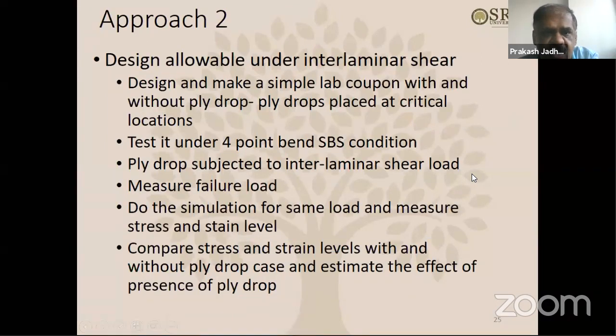What about shear? So for shear, we design another coupon. Here again, we thought let's design another coupon, okay, where we'll put the ply drop exactly at the location where interlaminar shear is more, like interlaminar shear level is very high. So we decided to use the short beam shear kind of specimen and use the four-point bend for short beam shear. Okay, so here ply drops will be subjected to the highest level of interlaminar shear load, then measure the failure load, do the simulations. Again, the same procedure basically, and also measure the initiation failure load using the acoustic emission, and then compare the stresses and strain levels with and without ply drop, estimate the effect of presence of ply drop.